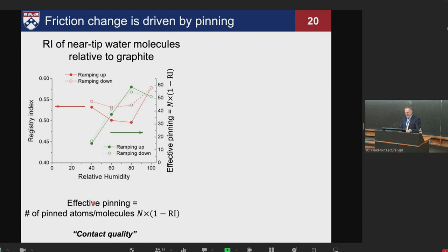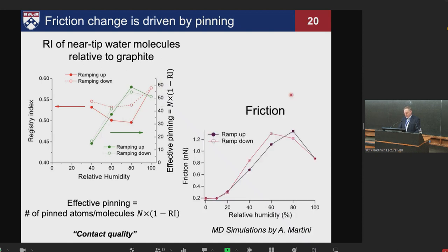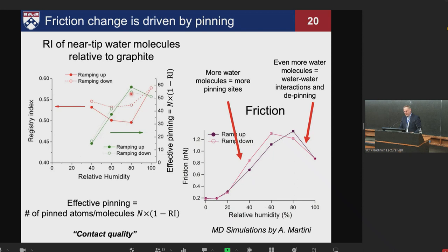So we define an effective pinning as the number of pinned atoms times 1 minus the registry index, right? That makes a low registry index give us high effective pinning, as it should. And so, okay, we see a maximum around 80, and that's close to where we see the maximum in the friction in the simulations and in the experiments, a little bit higher than in the experiments. But this is saying it looks like the pinning of those water molecules at the interface is important, okay? So more pinning sites, and we get higher friction.